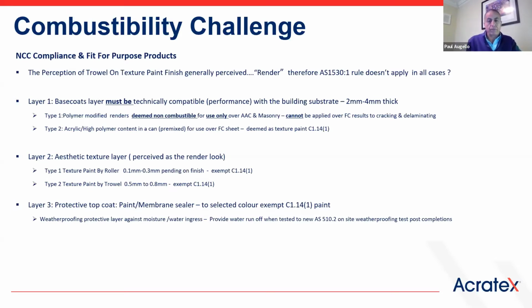If you took layer 1 being the base coat that we've spoken about, depending on the substrate, being masonry, all your masonry substrates, including AAC, that's where you can use a 1530 part 1 render, which is a cementitious material, a type 1. Whereas the type 2, the high polymer pre-mixed materials, which we believe are deemed a textured paint based on the interpretations the rule book allows you to work with, are suitable for all the fibre cement sheet systems on the marketplace. You would not use a type 1 cementitious material over fibre cement sheet, but you could do the other way around because of the technology.